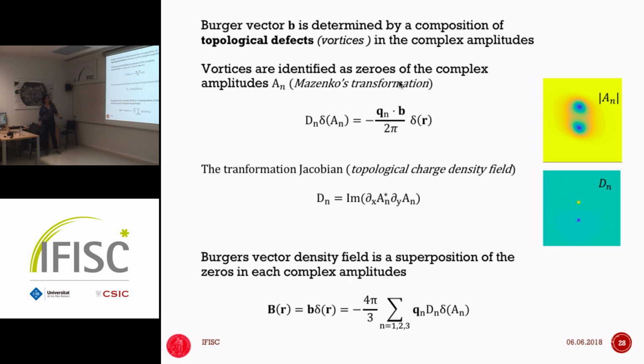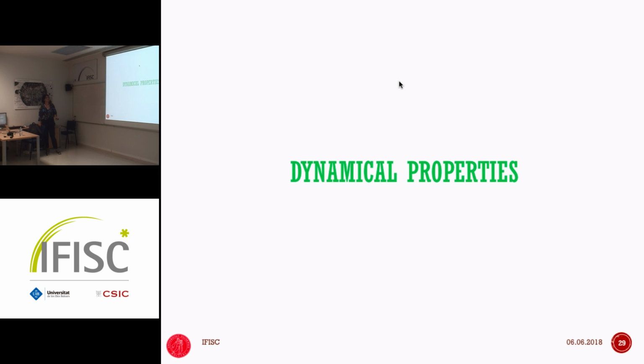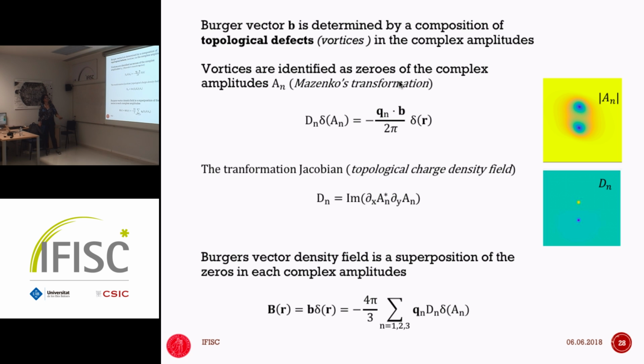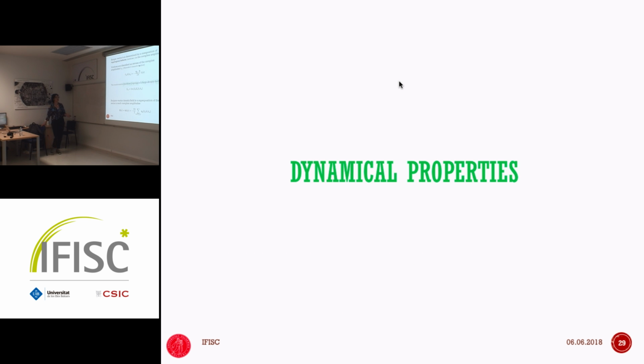Okay. So this allowed us to then define the Burgers vector in the hexagonal lattice through this combination of the wave numbers, the zeros in each of these waves, and the Jacobian transformation matrix. And it works. I haven't shown it here, but if you calculate the Burgers vector, you can actually get the Burgers vector density field, which is, again, a continuous variable. We have coarse-grained, and you can enter this into continuum models. But it comes directly from the microstructures. This is the important thing.